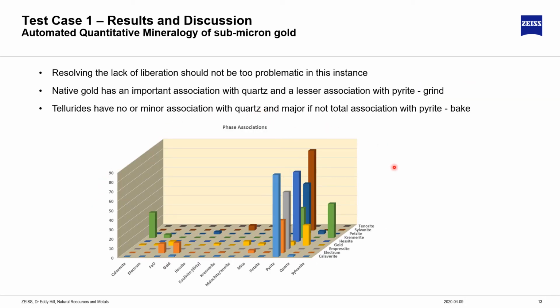So if we look at the associations of the gold-bearing phases and native gold itself to within themselves, but also to other significant gangue phases, what we find is that to resolve the lack of liberation, it shouldn't be too difficult in this instance. Native gold has an important association with quartz, and a lesser one with pyrite. Therefore, it's likely that in order to liberate the gold, all we need to do is grind further. There's an issue of granulometry.